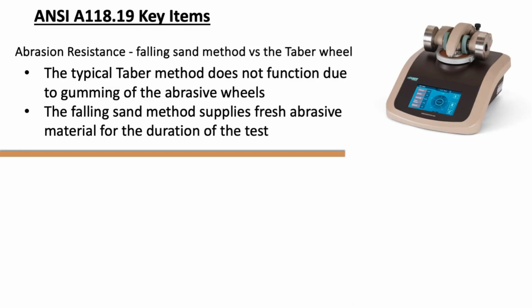You also did the abrasion test. So that's the Taber wheel on the right. Now, the typical method doesn't function with the premixed grouts because of the gumming of the abrasive wheels. Because remember, it is a compressible material, not a hard material like a cement or an epoxy. So they actually had to use a falling sand method to supply fresh abrasive material for the duration of the test.